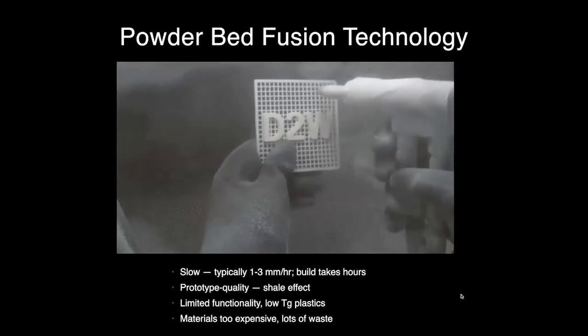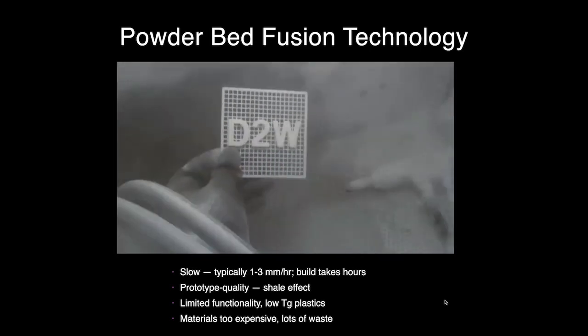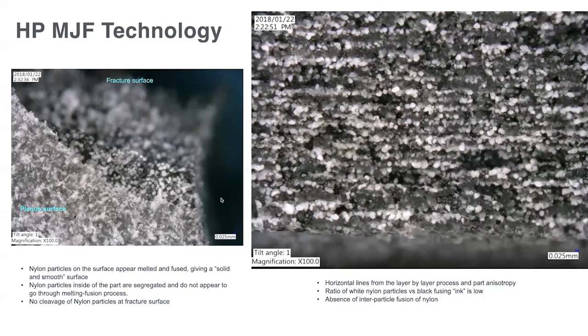But most importantly, because of the high molecular weight and the fact that polymer properties are derived from chain entanglements, you could crack open these products made by laser sintering, and you could see the deposition of particles layer by layer. In fact, you can see the whole particles. They're barely blended in. That's because of the transient nature. People are trying to go fast, and you have a lot of porosity, and you don't have the full maturation of the chain entanglements between particles like you do at the center of a particle.